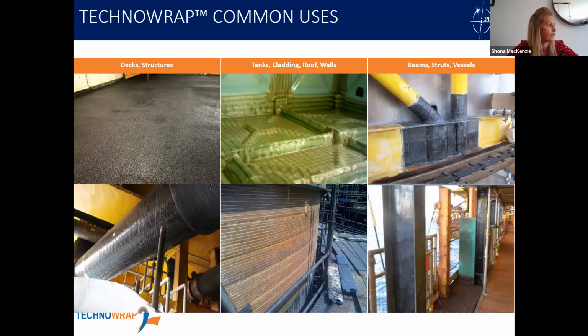We do require good surface preparation in essentially the landing areas for our composite repairs, as with any composite. SA 2.5, so like grit blasting or sand blasting, is the preferable method of preparation. However, we can also accept mechanical preparation, so ST3 prep, and on very few occasions hand preparation. You just don't get the same quality of adhesion when you use hand preparation, but if it's external corrosion and very low pressure lines, then we may be able to consider it. But Gareth will touch on the technical detail on that further in the presentation.